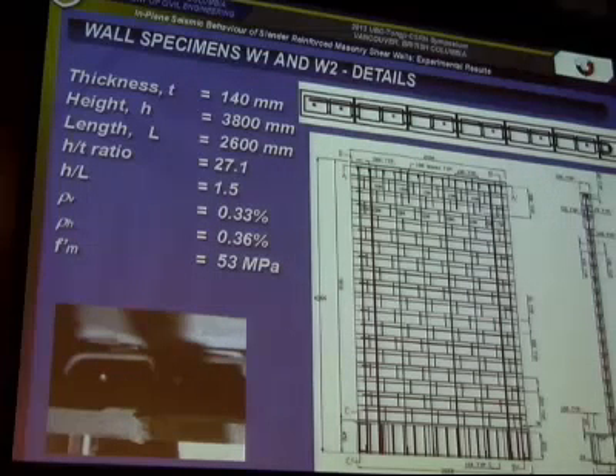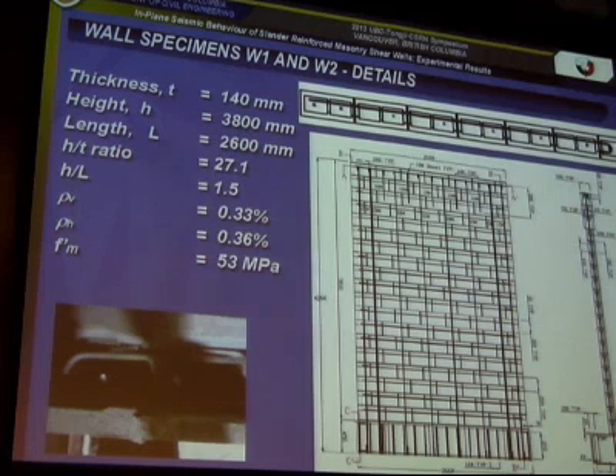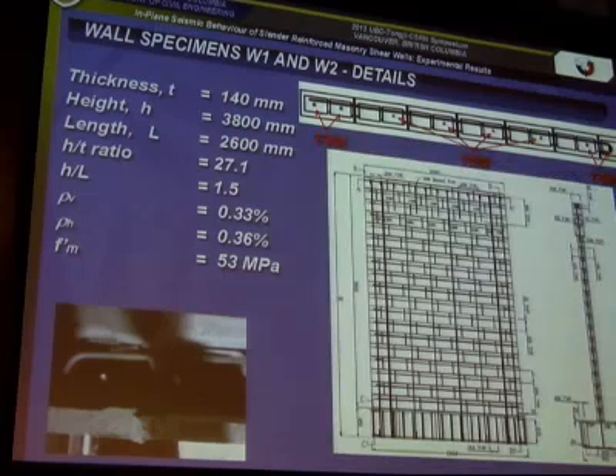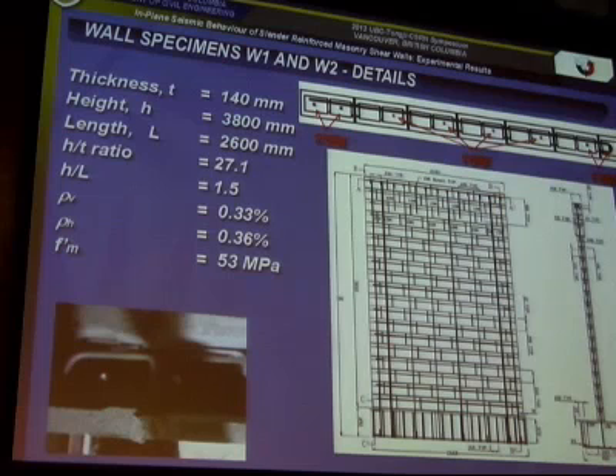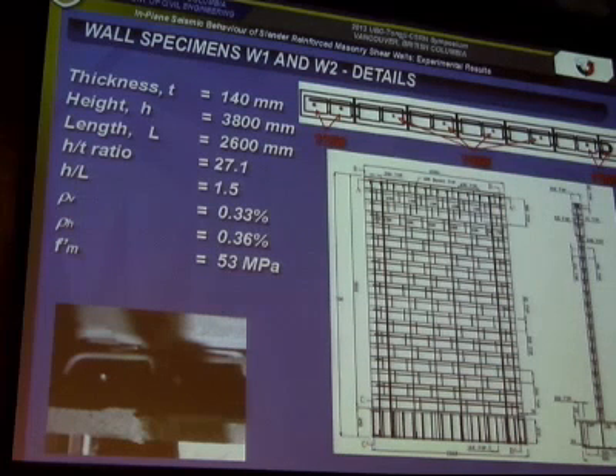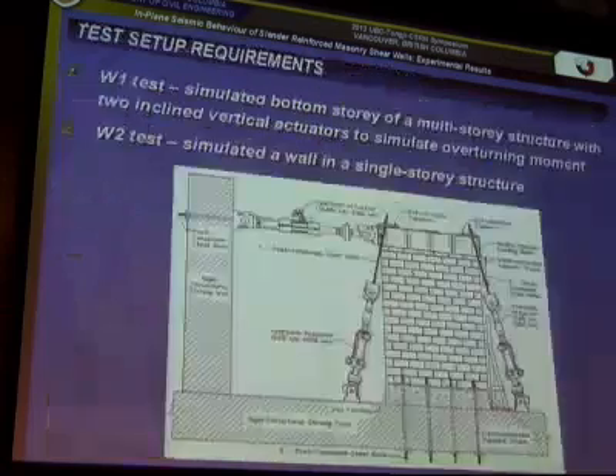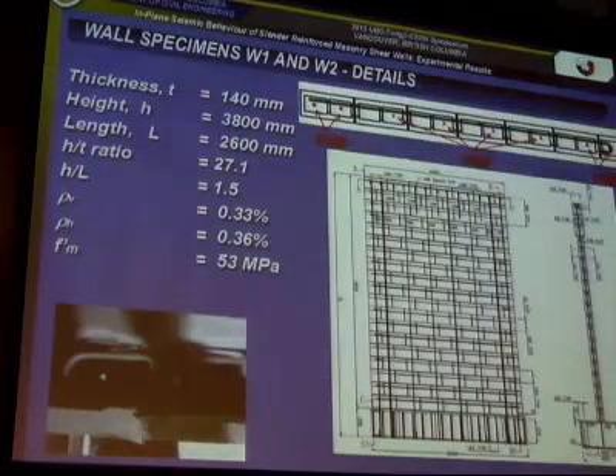So the two tests conducted so far were on identical specimens with geometric properties resulting in a height-to-thickness ratio of 27.1, which is about double the current Canadian limit on these walls, and an aspect ratio of 1.5. The vertical reinforcement ratio was 0.33% and consisted of two 15-millimeter diameter bars in the exterior two cores of the wall, and four 10-millimeter diameter bars spread throughout the center. The horizontal reinforcement consisted of a single 10-millimeter diameter bar at every course height, so every 200 millimeters.